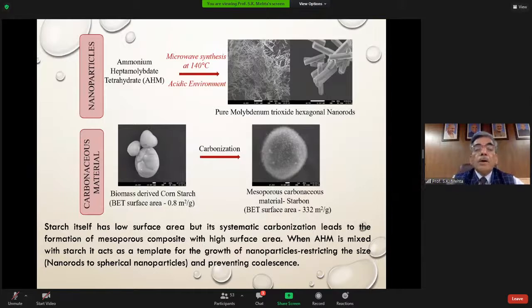Now, here is a brief of how this was produced. We started with ammonium heptamolybdate tetrahydrate, AHM, and using microwave synthesis at 140 degrees in an acidic environment, we get pure molybdenum trioxide hexagonal nanorods. So this method is also quite already established. Then next was to produce carbonaceous material. And for that, biomass derived cornstarch having BET surface area 0.8 meter square per gram. And after carbonization, we get the mesoporous carbonaceous material, which is called Starbon. So starch itself has a low surface area, but its systematic carbonization leads to the formation of mesoporous composites with high surface area. So that is the purpose.